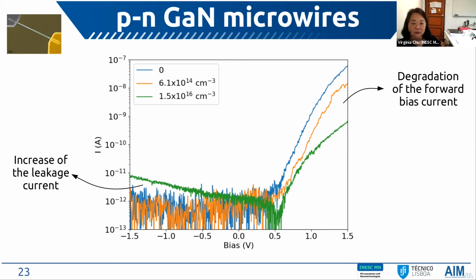What about if you fix a fluence and you expose it over long times? Do you also observe a degradation with that? Sorry, I'm not sure if I understood. If you have the wires, you fix the fluence, but you look at the IV curves versus different times of exposure. Do you also observe degradation with time of exposure? Actually, the fluence is a parameter which depends on the time of irradiation. Oh, I see. So it's not just the intensity. Exactly. We have a certain proton flux, and the fluence is calculated by multiplying the flux with the irradiation time. The flux is constant. Okay, so I didn't understand that.